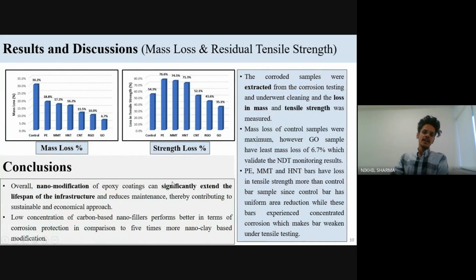From mass loss and loss in tensile strength, we can see the least mass loss and least loss in tensile strength was for GO-based coatings, whereas for plain epoxy coatings, mass loss is approximately half for the uncoated rebar.